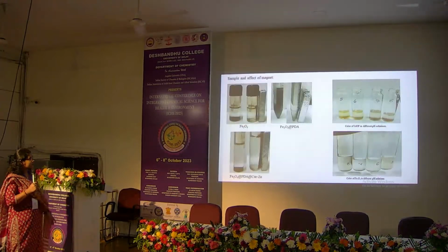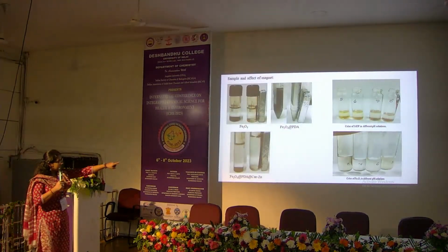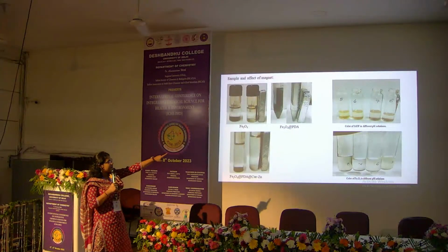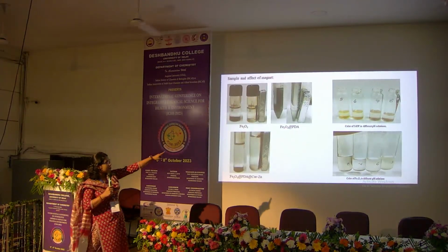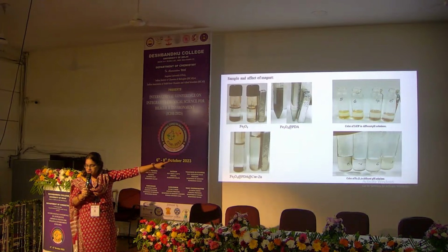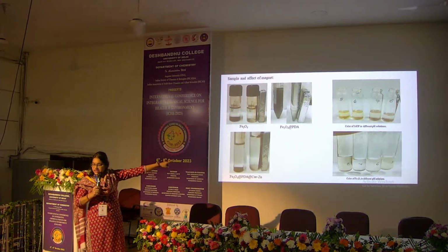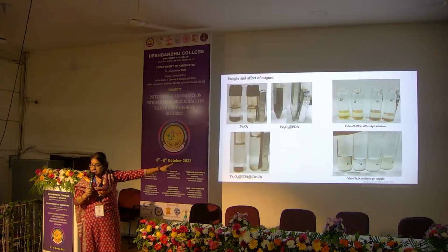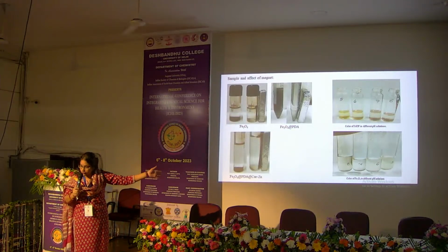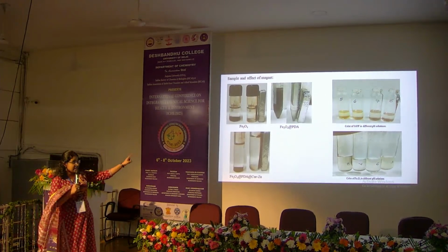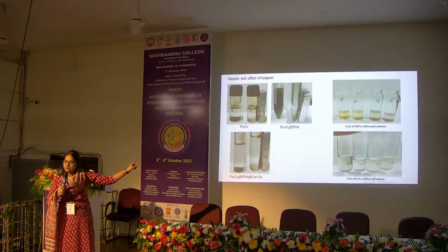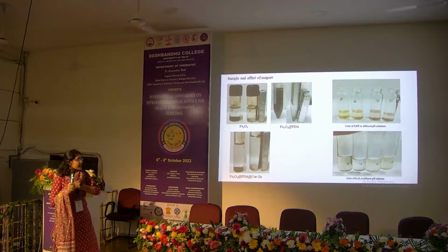Next, sir. So these are my compounds, and this color is MOF, in different pH solutions. Raw curcumin is soluble in alkaline solution, but here in MOF it is not soluble in alkaline solution. As we increase the acidity, it is solubilized and releases a yellow color, that is, it becomes curcumin. Here, as it is linked with zinc in MOF, it doesn't solubilize in alkaline.